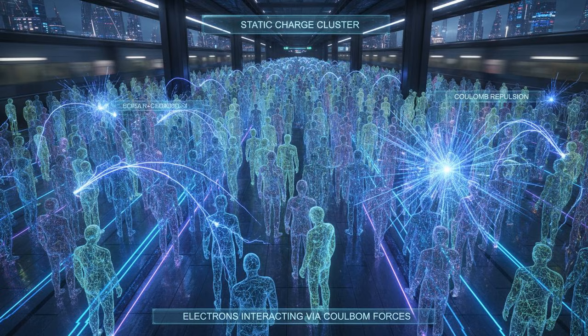Using our train analogy, the high-speed train has stopped. The commuters get off and are suddenly forced into a crowded room. Because they are no longer dominating the scene with their speed, they are forced to interact with one another. The dominance of kinetic energy is replaced by the dominance of Coulomb interactions, the repulsion between negative charges. McDonald and Bistritzer predicted that this magic angle of 1.1 degrees would be a playground for correlated physics.